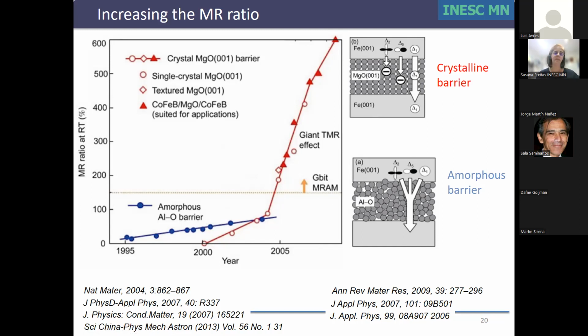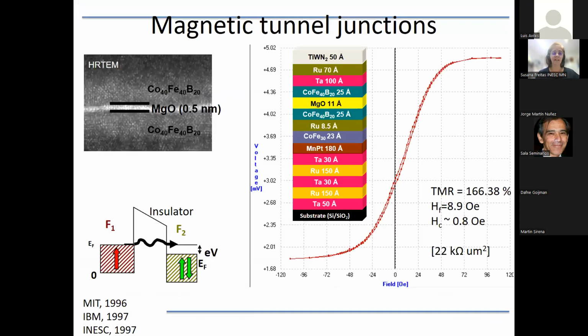So it was quite exciting, and in fact this is what people use now. I must say that this 600%, which is not observed in sensors, is observed in stacks, in multilayers, but not with sensor linear characteristics. In a sensor, as far as I know, the maximum magnetoresistive ratio that we have now, in 2022, is around 220%. So this means that there is still a lot of work required for a sensor to operate.